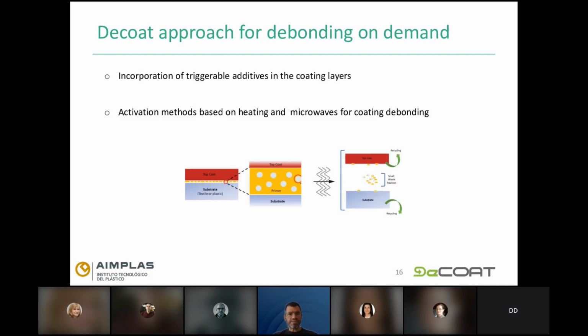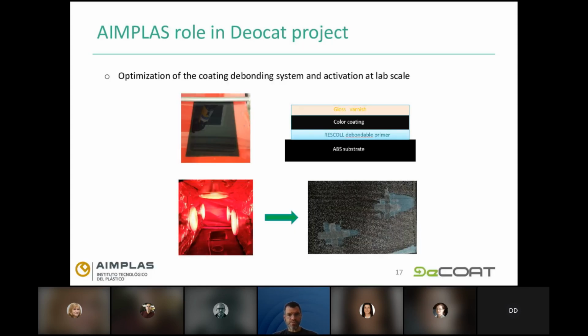So, the Decoat project approach is based on debonding on demand technology by means of incorporation of triggerable additives in the coating layers and the development of specific activation methods based on heating and microwaves for the debonding and removing of these coating layers from the plastic substrate. Just in a quick slide, let me show you some preliminary results about the task and the role of AIMPLAS in this project, which has been mainly related, in the first stage, to the optimization of the coating debonding systems at laboratory scale. Within this task, we have been able to apply the debondable primer provided by partner Rescoll.